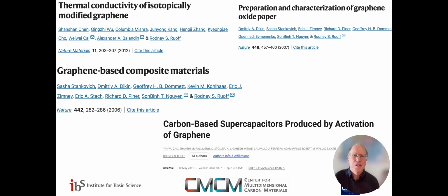Yeah, it's very interesting if we wanted to make C12 pure, which is not that hard. It's not that expensive compared to natural abundance. The thermal conductivity goes up dramatically, both for graphite and for graphene. Multilayer graphene, that will certainly be true, in case that's useful. For BN, we can isotopically label the boron. Nitrogen's already very pure as nitrogen 14. It helps. Two different elements, it's going to be lower thermal conductivity than graphene.